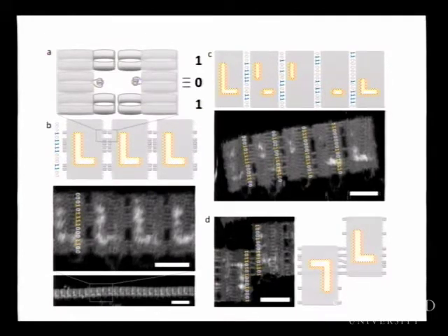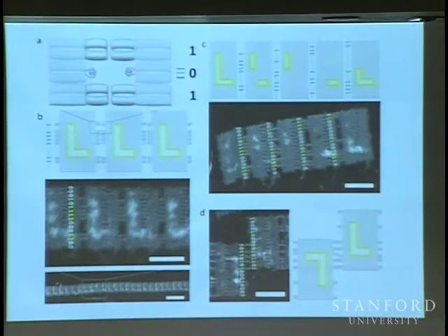One way is this. These are 3 origami. Along the edge of the origami, you either put in a DNA staple that makes the ends take on a rigid geometry, 2 little cylinders sticking out, or you leave a staple out and it leaves that scaffold an unstructured little loop that balls itself up, so you leave this little unstructured ball here. So now you have a binary sequence of either structured bits that can stick to each other or unstructured bits that should have, in principle, not a very strong interaction. They can have some interaction.